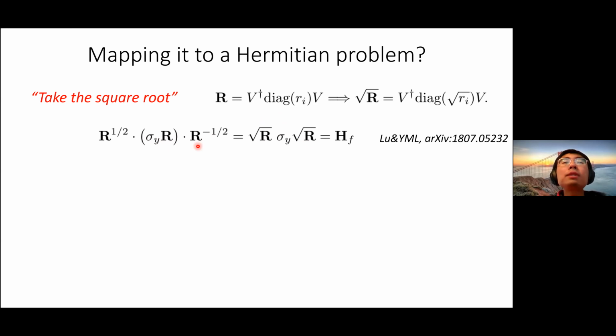The way to do it is to use a similarity transformation: you left multiply by the square root of R, and right multiply by its inverse. This similarity transformation does not change the eigenvalue, in other words it doesn't change the spectrum of the system, but it does make the matrix Hermitian.